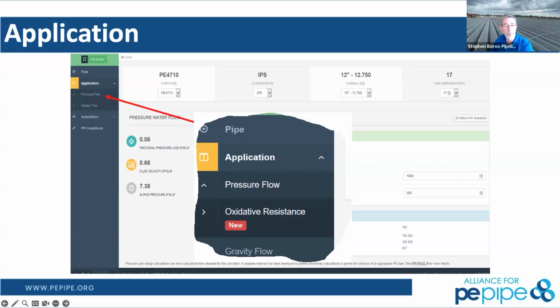You know, that's an excellent point, Richard. I didn't touch on that point, but that is really good. And that'll let you look at that chlorine categorization that we have on polyethylene materials today. So if you didn't know, all C906 standards and C901 require a polyethylene material with a CC3 rating. So if you go through these oxidative resistance calculations with your exact water conditions, you will see that will give you a true 100-year design life against oxidative failure. So that's really key. That's going to be eliminated from a failure mechanism in your system.